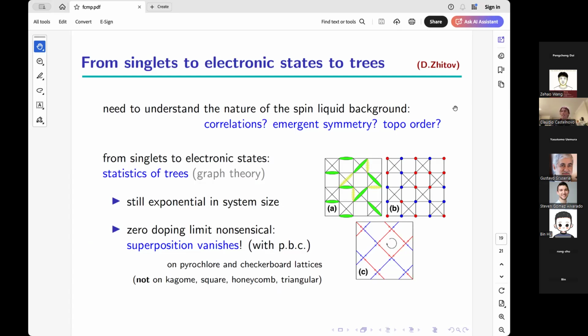And eventually Daniil did some beautiful work using the statistical mechanics of graph theory of objects called trees and forests, and was able to prove it mathematically. This tells us that basically the zero hole limit doesn't exist. It's not a problem experimentally because low doping is as good as zero doping. Actually, achieving exact zero doping is probably more difficult than low doping, but it's a problem theoretically because the holes create this state and are in some sense needed. They are the simplest example of an open boundary condition that allows this superposition not to vanish.